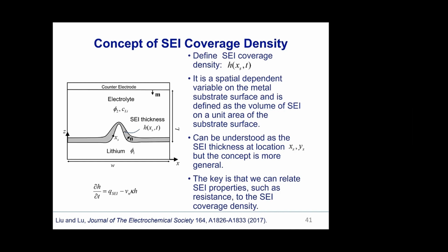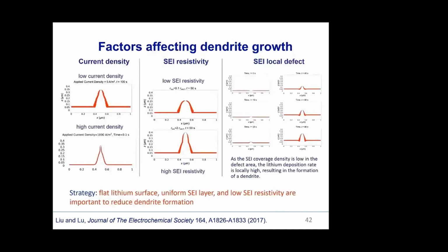Now, by coupling the dendrite growth and SEI growth on top of the lithium metal dendrite, we can predict battery performance, especially for lithium metal batteries. We analyzed various factors, including current density, SEI resistivity, and SEI local defects, to observe how they affect the dendrite growth. The key conclusion is that a flat lithium surface, uniform SEI layer, and low SEI resistivity are important to reduce dendrite formation.